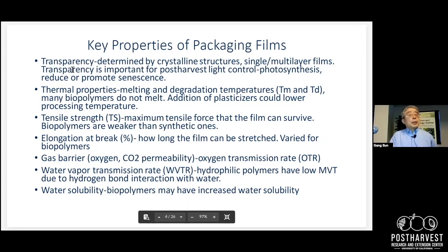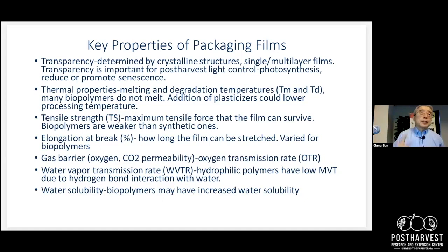So we do look for how clearly we can see the product through these packaging materials, and the transparency is mostly determined by the polymer's structure, which is what we call the crystal structure. If there's more crystalline, the film becomes stronger, but it becomes cloudy, and so you lose the transparency. So if you want to maintain the transparency, we have to keep the polymer in the so-called amorphous. Amorphous is just like a glass. If the polymer becomes crystal, it becomes cloudy and opaque. So transparent, just like a glass. A glass is 100% amorphous.